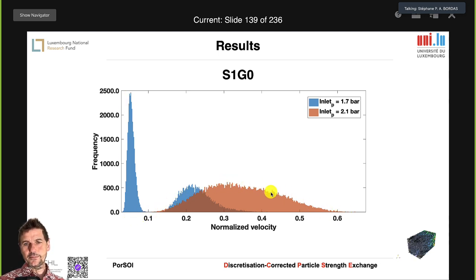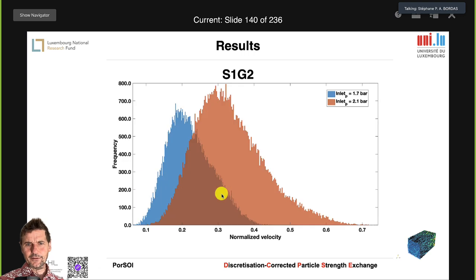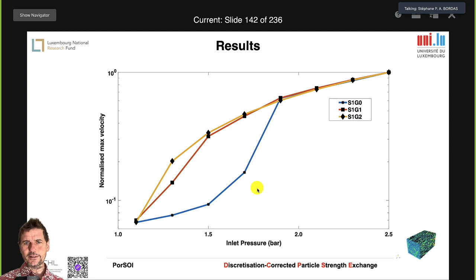And you see this little bell-shaped curve, which is centered around 0.35, right? And that tells you what the distribution of the velocities is. And this is in the actual microstructure. Now, if you look in the higher porous case, what you see is that there is almost no difference between the 1.7 bar and the 2.1 bar. And so the results look like that.